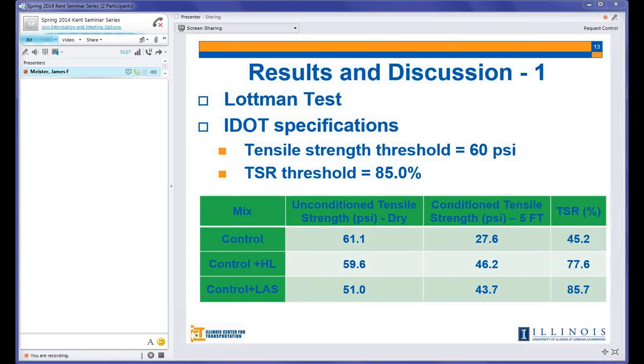The first column is the unconditioned tensile strength. There is no conditioning. The second column is the conditioned tensile strength, which is after 5 freezing-thawing cycles. The TSR is the last column. If you look at the first column, we can see that the control mix barely exceeded the threshold, which is 60 psi.